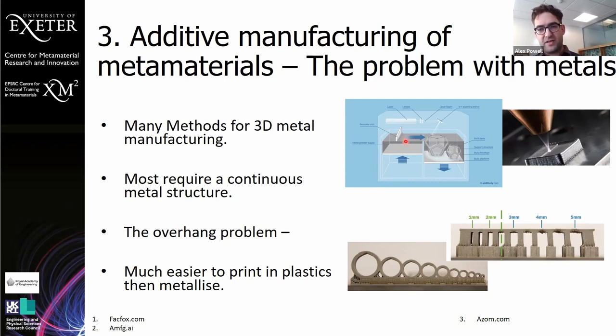You have a bed of powder that is heated up to just below the melting temperature. You scan over with a laser and it melts the 2D cross section of whatever you're trying to print. Then you drop this layer down, put some more powder on, and repeat to build your structure. That works pretty well. These machines are quite big and expensive because you have to have very tightly controlled environments, as the powder gets a bit explosive otherwise. But you can make really cool structures from them. But one of the things all of these metallic methods suffer from is this overhang problem.